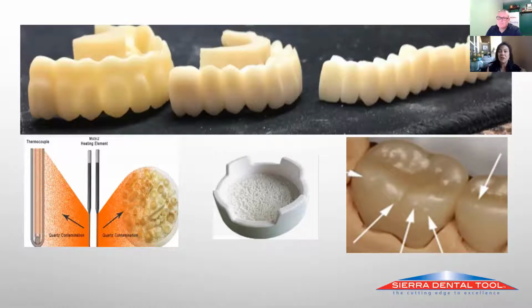These restorations on the top of the screen were all milled out of the same shade material, and they were put into 3 different furnaces with 3 different levels of contamination, and you can see we got 3 different shades. That's not because of the material, that's because of the contamination that was depositing on each restoration out of each oven.